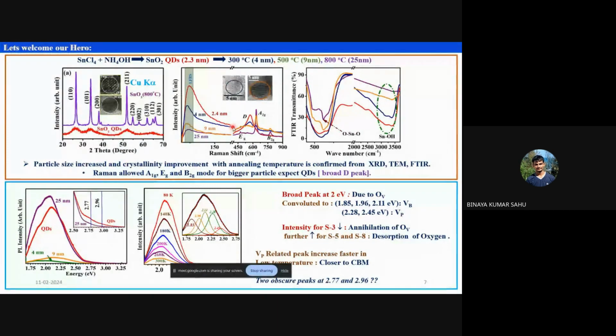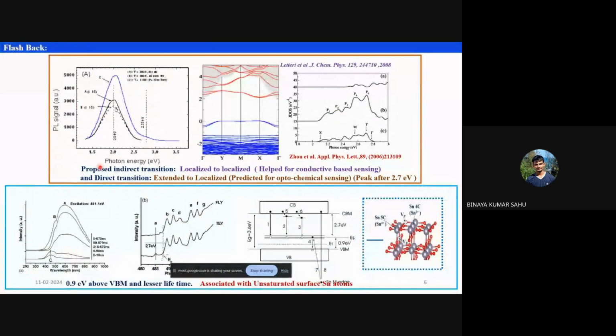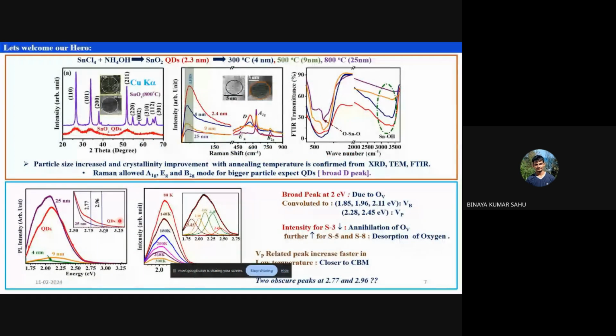And these are the Raman spectra. These are the FTIR spectra, and this is my PL data. This is the PL data that I have taken from my material, and this is exactly the same as what other experimentalists have proposed. You will get a peak around 2.0, and there will be a small hidden peak around 2.77 and 2.96.